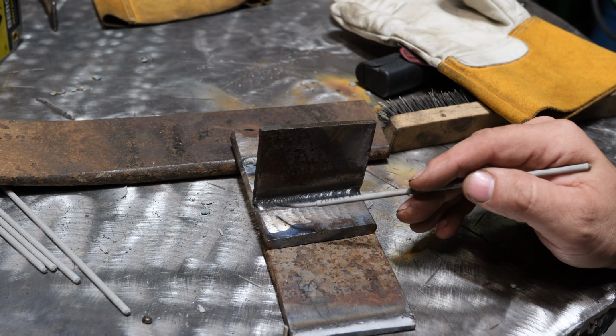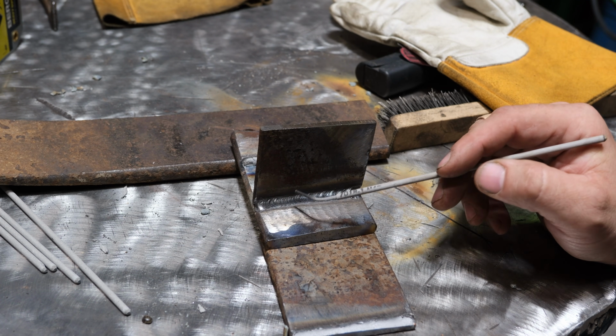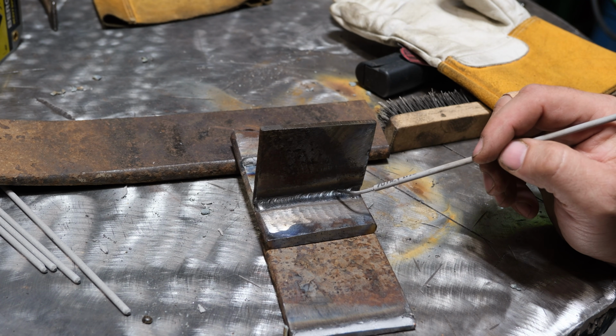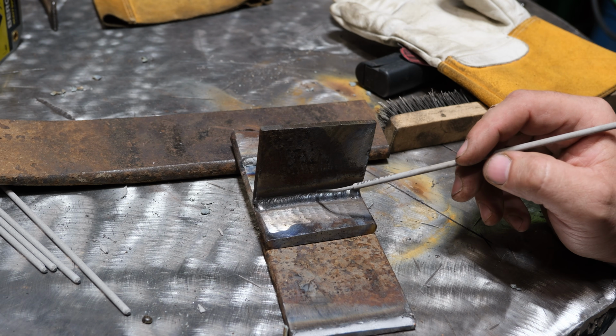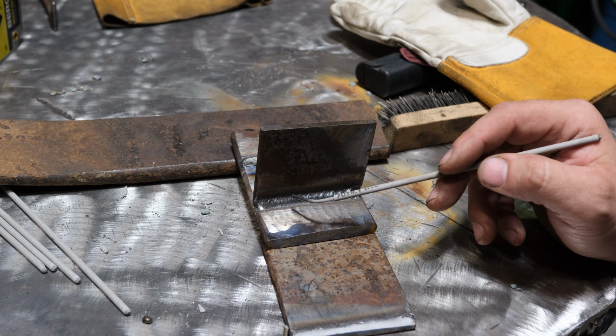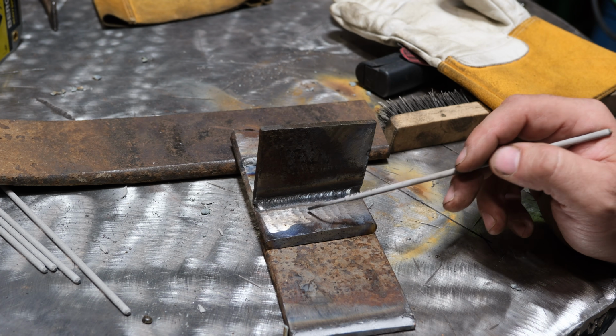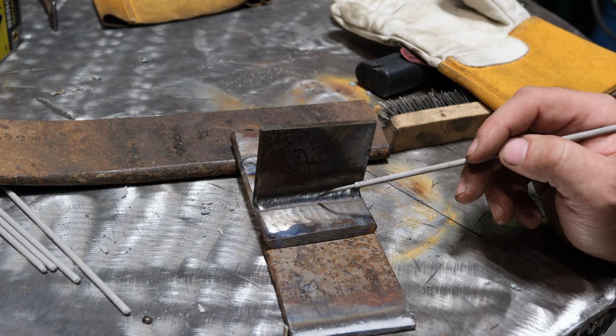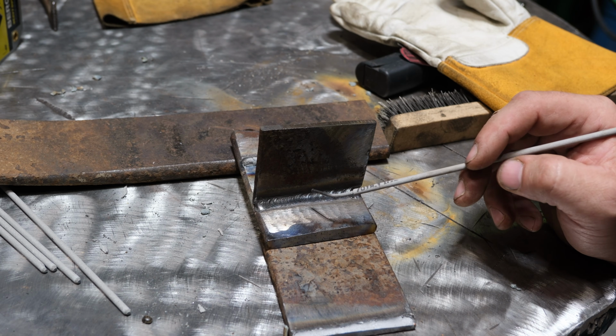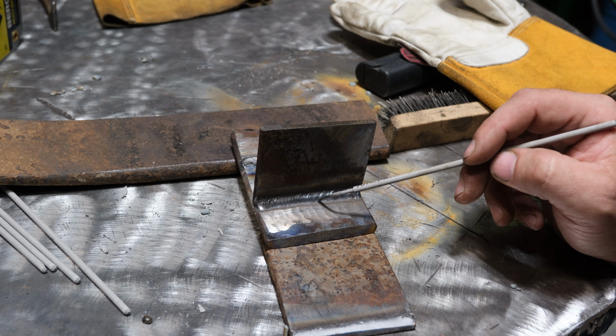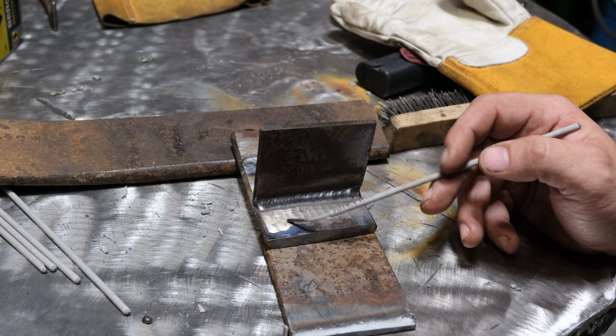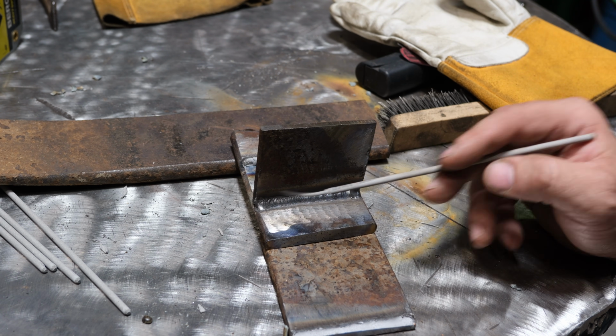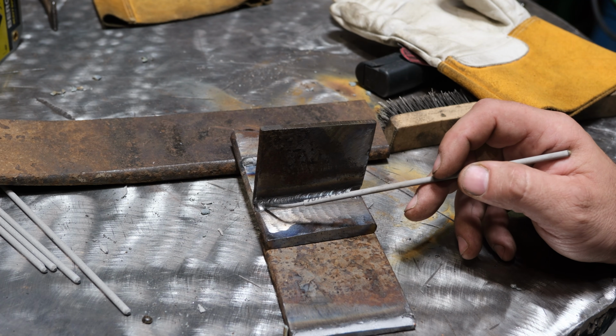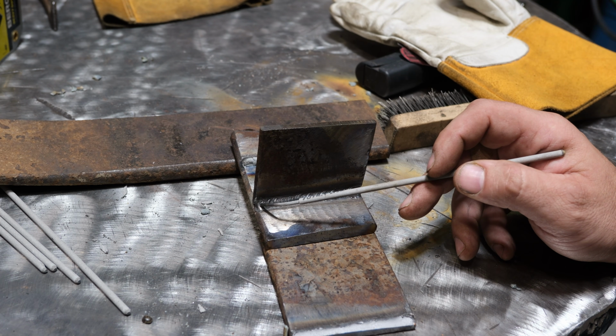So once again, we have made it through the welding process, and I don't see any evidence of cracks or weld failures or anything like that. So that is a great sign. But once again, this is identical to what we just tested that broke, and we don't want this to break, because if it breaks, well, it's of no use to us, right? So what we're going to do is I'm going to take that torch, put a lot of heat into this, and get it to a dull red.